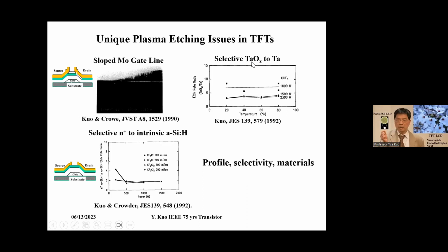Another unique point for TFT is the metal gate, which is usually made of metal. To make it highly reliable, the dielectric usually can be several layers. For the metal layer, people anodize it to make sure it's totally covered, then deposit a separate gate dielectric layer. For contact, the metal oxide has to be etched selectively to expose the metal. This result shows it can be achieved with proper plasma chemistry. Those are unique examples of parts of TFT production that use plasma etching technology.